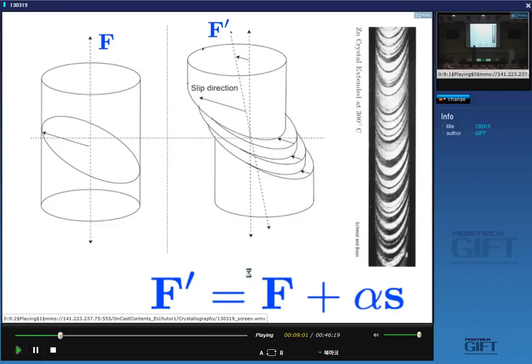When we do such an experiment, we put our single crystal in a tensile specimen and pull it, so the force axis is not allowed to rotate — it's constrained to move along the vertical axis. Instead, the crystal itself will rotate. So it's relative motion that's important: if you confine the force axis to be constant, then the crystal planes will actually rotate.